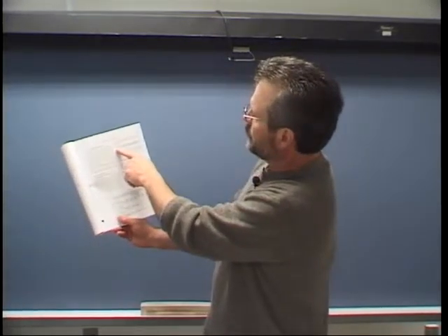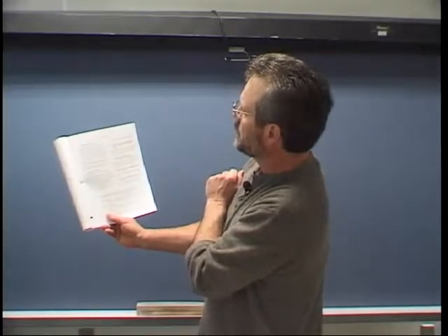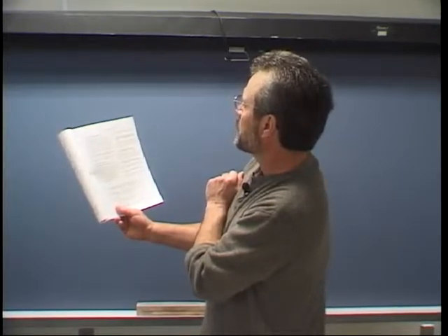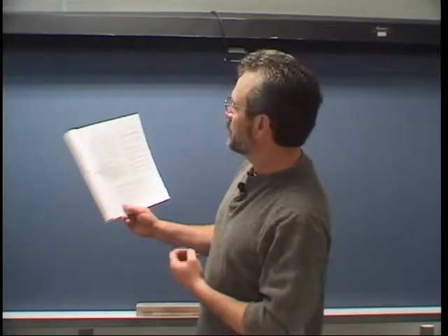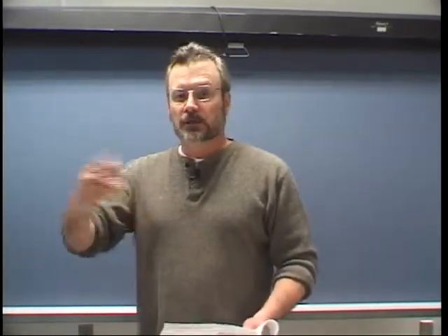Here we go. 3.5.2, tensile strength, nick break, and bend test procedures for butt welds. It says the specimen shall be prepared for tensile strength, nick break, and bend tests, and the test shall be performed as described in 2.6. So it's referring us back to another section, another paragraph. And it says the tensile strength test may be omitted, in which case the specimens designated for this test shall be subjected to the nick break. So under the code, typically it'll say 2 nicks, 2 tensiles, and two root bends. But if we want to omit that, that's okay. But we'll have to take those 2 tensiles and we'll do nick breaks out of them. So now we're going to do 4 nicks instead of 2 and 2.